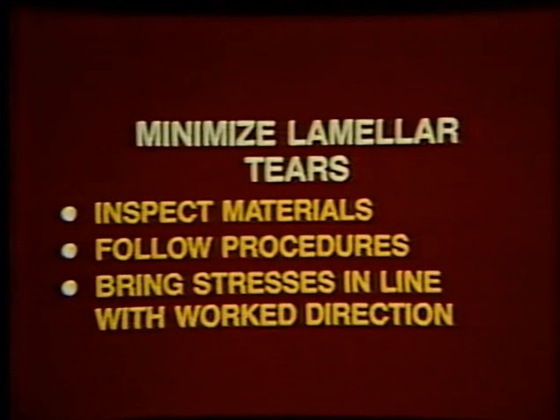They occur when the through thickness of the plates cannot withstand the pulling effect of the shrinking weld during cooling. Lamellar tears generally occur in areas of the base metal where inadequate refining is present. To minimize or prevent lamellar tearing, ensure careful inspection of the materials prior to welding. Make sure that the welding procedure is being followed, and attempt to design joints so that shrinkage stresses are brought more in line with the work direction of the material.